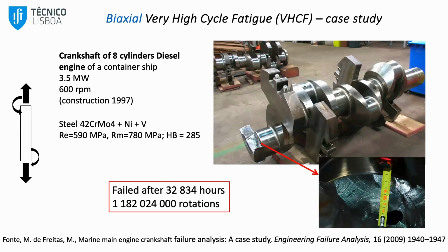Okay, so this is a case study that we have studied in our lab. It's a well-known mechanical component, a crankshaft. In this case, it is for an 8-cylinder diesel engine with a power of 3.5 megawatts and around 600 rotations per minute, which means that in this particular case, the main efforts are the torsion and the bending efforts. So this ran for around 33,000 hours, which means a huge number of rotations. So this is the motivation for this kind of studies.